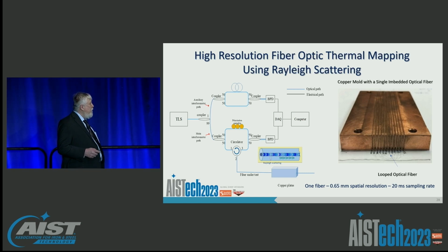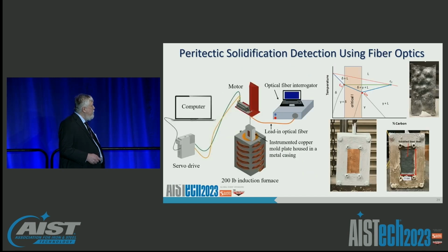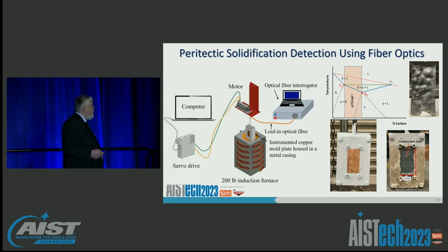So this is an experiment that we've done in our labs that shows a mold where the fiber has been woven back and forth within this mold plate. And then we put it into a system. There we immerse it in molten steel to do a heat transfer measurement and actually extract the shell growth and measure that shell growth. And we've used this largely in our labs to study peritectic behavior. Peritectic shift is a function of chemistry.